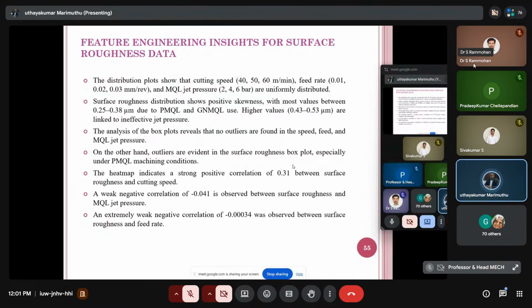The surface roughness distribution shows positive skewness with the most values between 0.25 to 0.38 microns due to PMQL and GNMQL use. Higher values of 0.43 to 0.53 are linked to ineffective jet pressure. It is the inference from our study. The analysis of the box plot reveals that no outliers are found in the speed, feed, and MQL jet pressure. On the other hand, outliers are evident in the surface roughness box plot, especially under PMQL machining conditions.